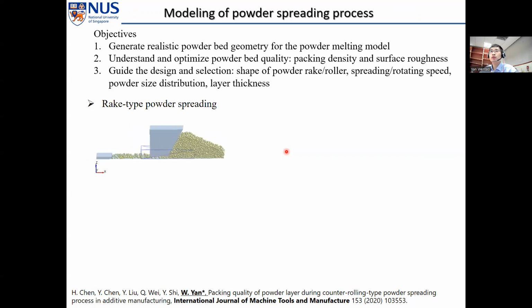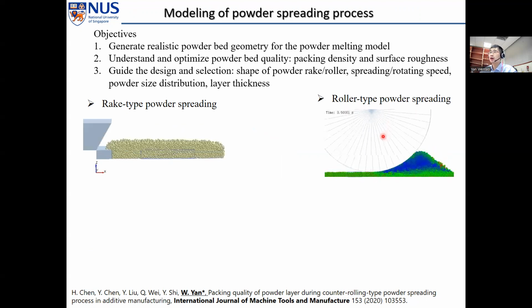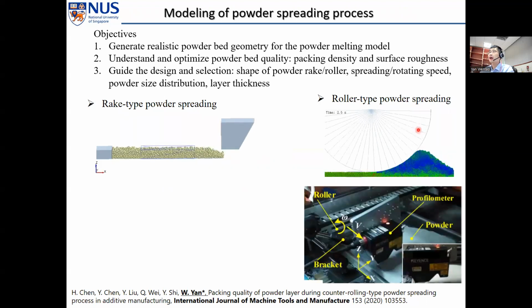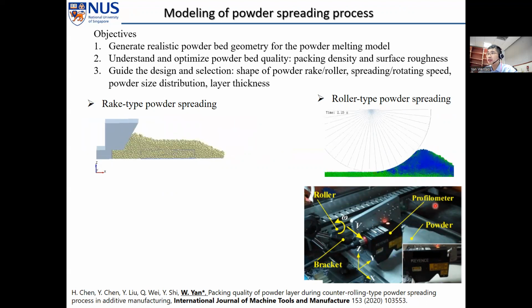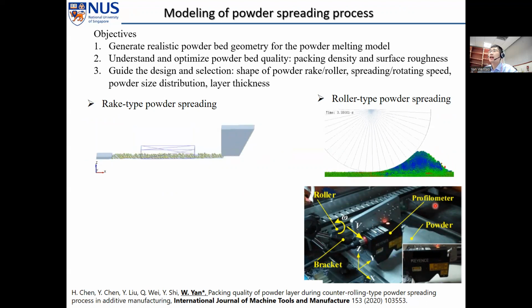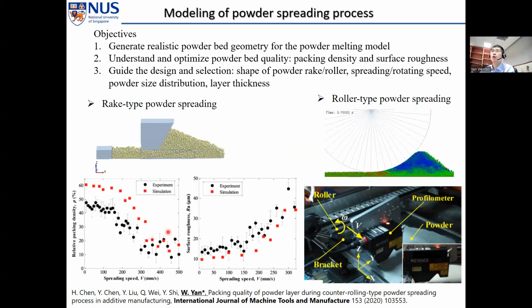There are mainly two types of powder spreading machines. The first one is the rake type, where the rake is translating over the powder bed. Another is the roller type powder spreading, where the roller is rotating and translating. We have done extensive experiments to validate these models. For the roller type powder spreading, we add a profilometer here so that after powder spreading, we can measure in situ the surface configuration of the powder bed so that we can evaluate the surface roughness. And after this process, we can collect the powder and measure the relative packing density of the powder bed. And then we can do a quantitative comparison with the simulation.